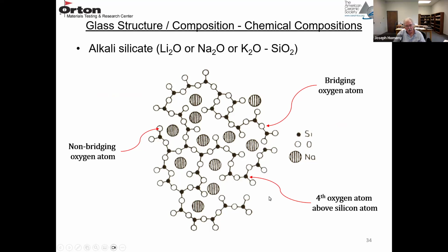So this is a model of the actual glass structure. The black circles are silicon, the open circles are oxygen, and the crosshatched circles are sodium. Here's your tetrahedron. Again, the fourth oxygen would be above the silicon atom. So here's your basic structural unit. Here's one tetrahedron and a second tetrahedron bonded with a bridging oxygen. And then this is a non-bridging oxygen right here. It's not connected to another silicon in a tetrahedron, but it is sitting next to an alkali ion, which balances the charge. So you can see how the addition of sodium, in this case, disrupts the three-dimensional structure.